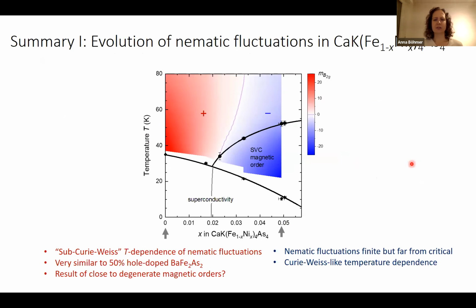So let me summarize my first part. Phase diagram of the 1144 and the B2g elastoresistance coefficient here. On the high nickel content side, the magnetic side, we do find finite nematic fluctuations, even though this is all tetragonal and the transition is also to a tetragonal magnetic state. And these fluctuations are far from critical, but they nevertheless have a Curie-Weiss-like temperature dependence. On the other hand, we find evidence for what we can call a sub-Curie-Weiss-like temperature dependence of the nematic fluctuations on the optimum TC sample, very similar to the overdoped 1-2, the equivalent one. And we think that might be a result of the magnetic orders being close to the transition line between the SVC phase and the stripe-type phase.